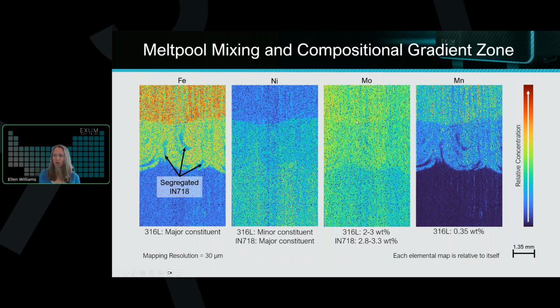melt pool. We can also point out something like molybdenum, which has a very similar composition within both of these alloys, and we can see there's hardly a gradient across these two materials, because it's around the 2 to 3 weight % in both materials. We see a fairly uniform composition of molybdenum across the same area. Manganese is a minor element. It's less than 1 weight % in the 316L, and so you can see that it follows the same pattern as what we see on the iron, since it's primarily only in the 316L and not in the nickel alloy.